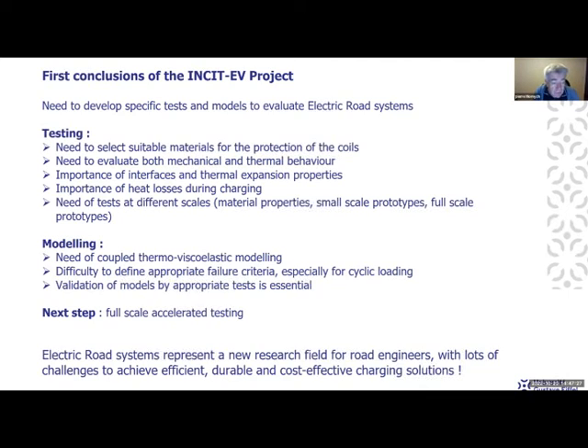And we found that it is necessary, and we tried to do tests at different scales, starting with material properties, small scale laboratory tests, and then going to validation by full scale tests or full scale prototypes. And for modeling, there is a need to develop coupled thermoviscoelastic models to take into account both the thermal behavior and the mechanical behavior. And there is also a difficulty. It is necessary to define appropriate failure criteria for these solutions, especially for cyclic loading. You cannot use just the standard failure criteria for asphalt materials. And validation of the models for appropriate test is essential.